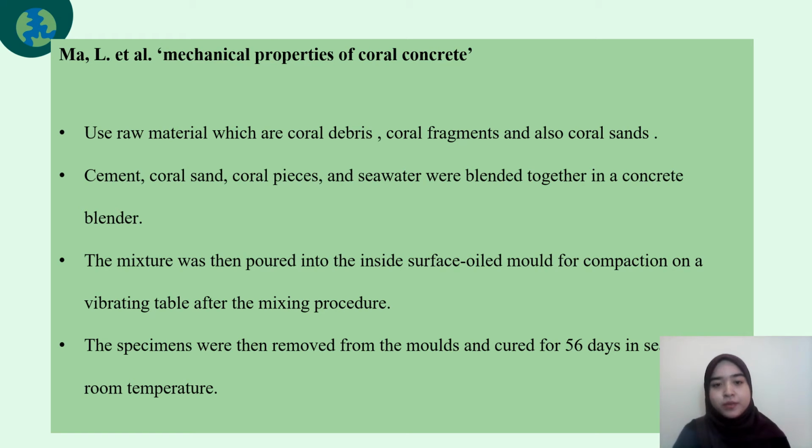The mixture will then be poured into an inside surface oil mold for compaction on a vibrating table. After the mixing procedure, and after the mixture is ready and we can place out the mold, the specimens were then ready to remove from the mold and cure for 56 days at room temperature. After that, the specimen will be tested in terms of its mechanical properties for compressive strength.